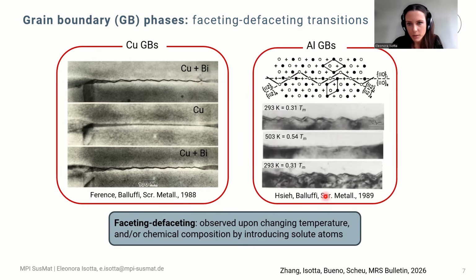Here is another example of such faceting-defaceting transitions happening in aluminum grain boundaries, where as a function of temperature, the same grain boundary also went from faceted to defaceted back to a faceted configuration upon increase and then reduction of the temperature.